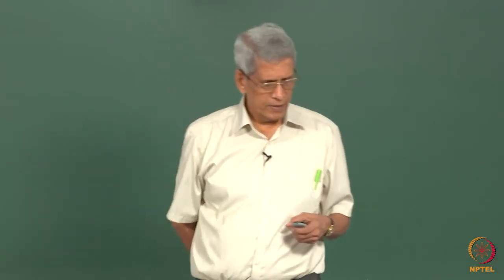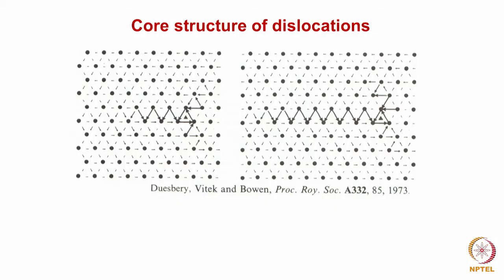then what happens is that at different stresses, here is a very small stress that's essentially something like 1/100th of the shear modulus. It's a quite high stress. When that stress is being applied, the displacements, now you can see that an asymmetry has come. Only in this direction the displacement is maximum and the displacement in these directions has reduced. The same thing you can see when the magnitude of the shear stress has been increased. You can see that now it is lying in only one particular 110 type of a plane, correct?